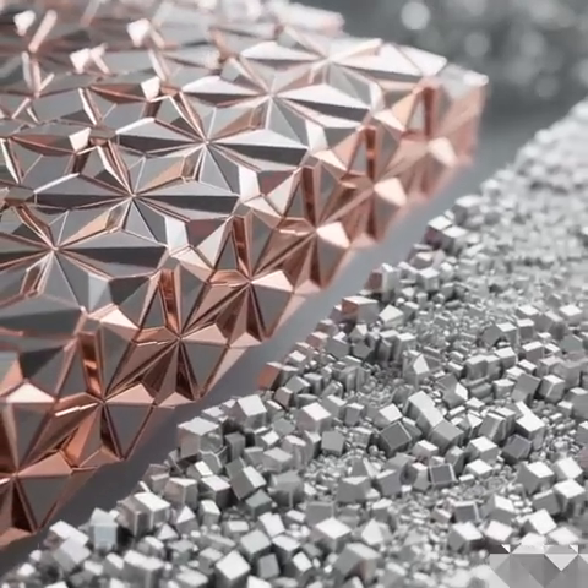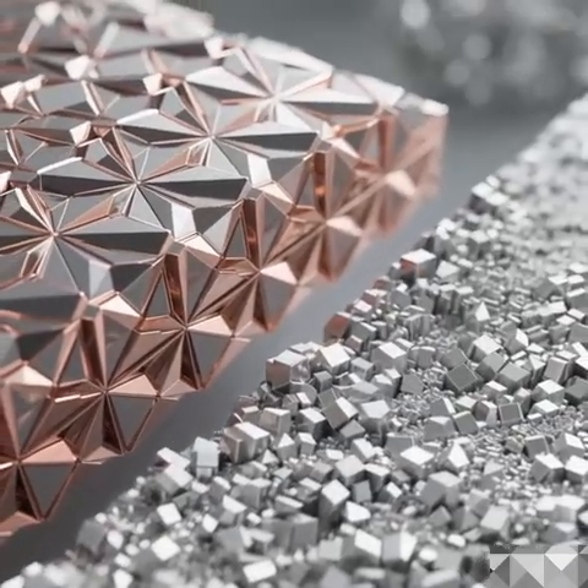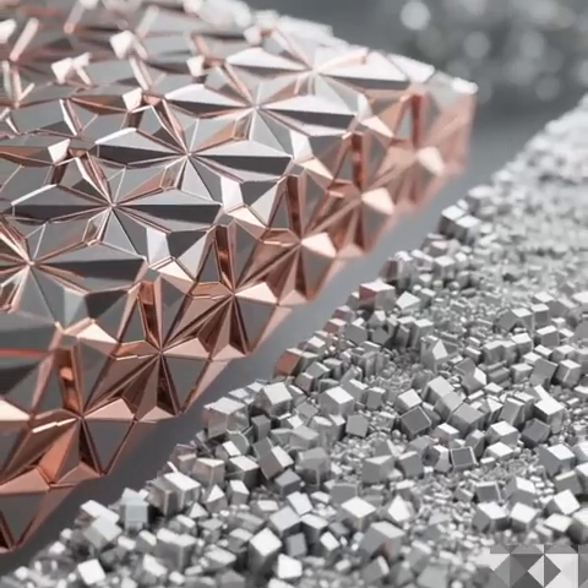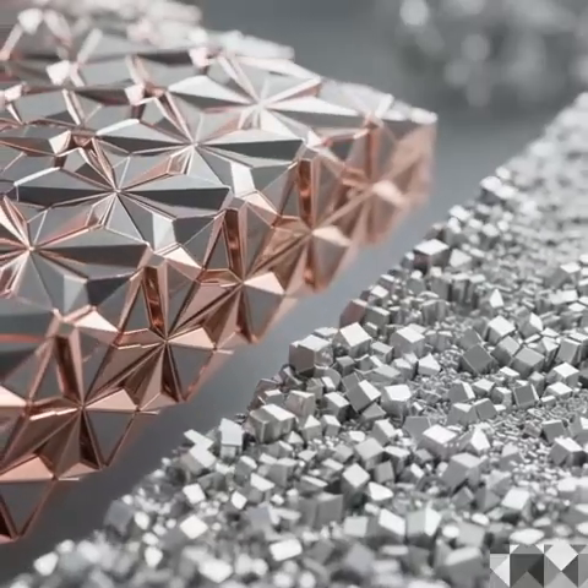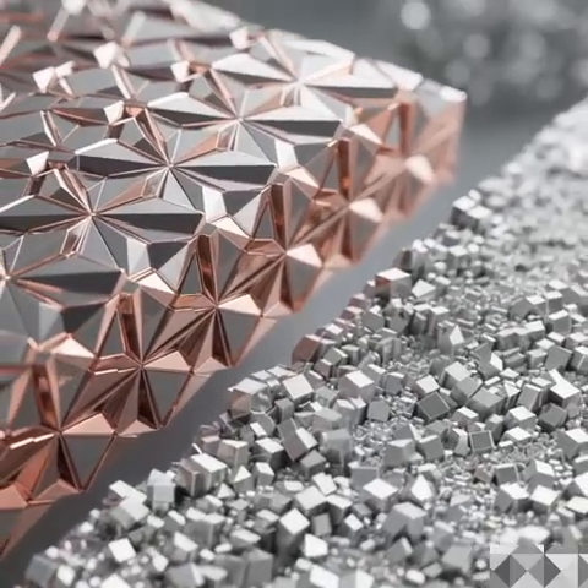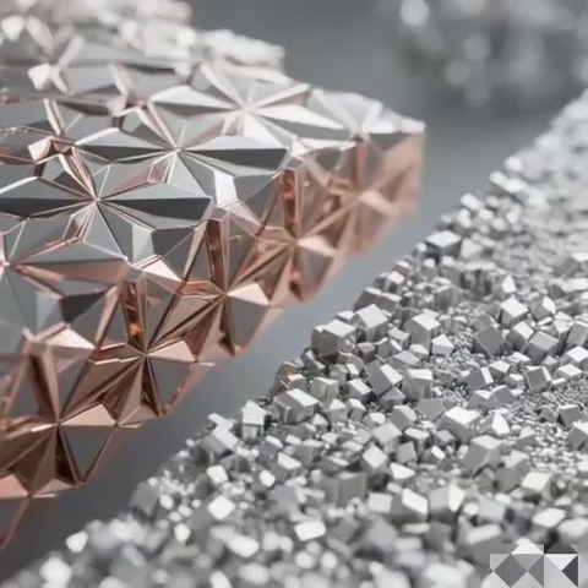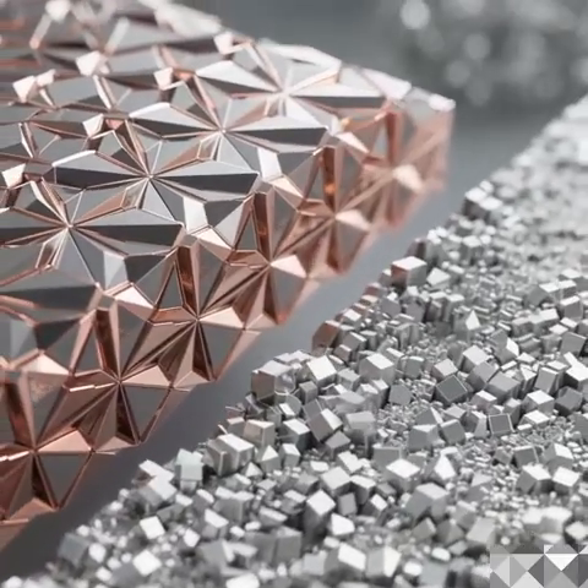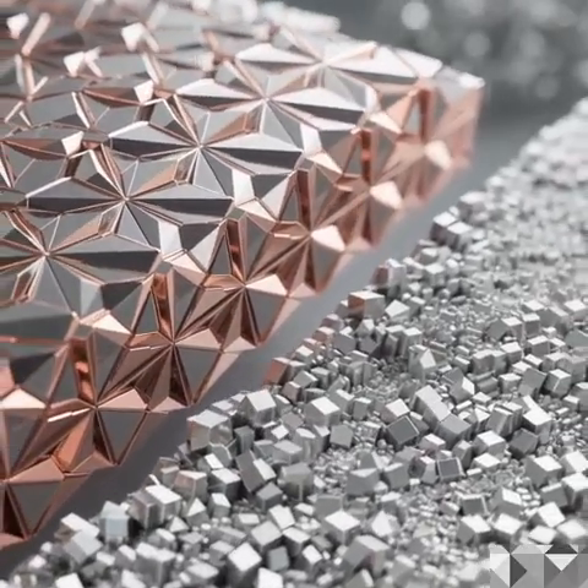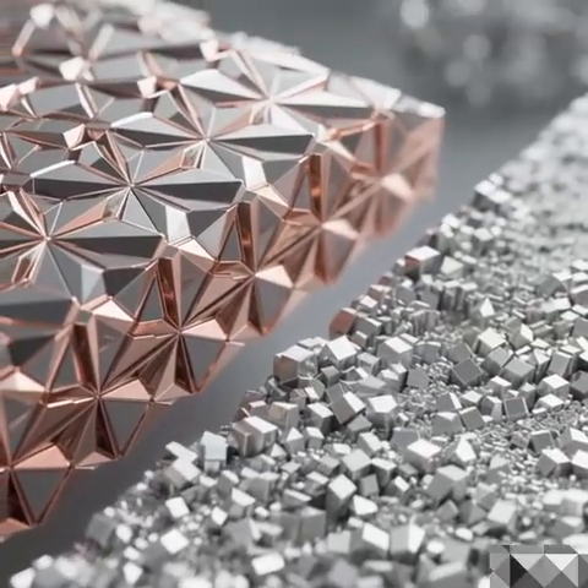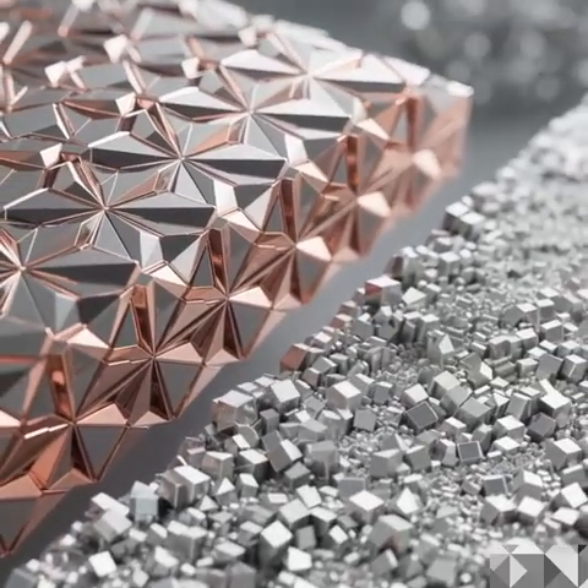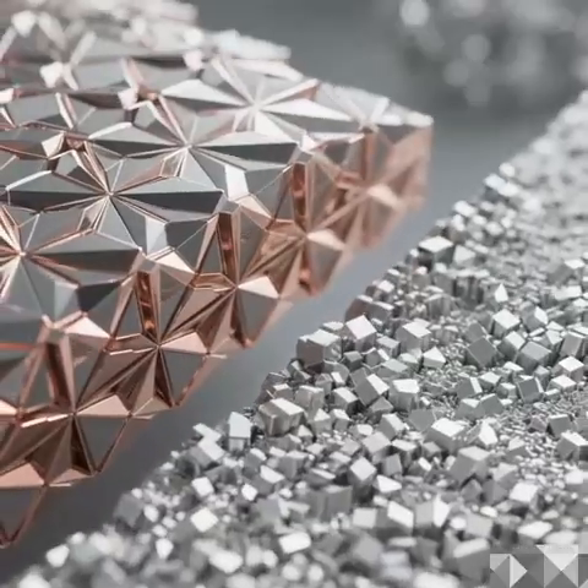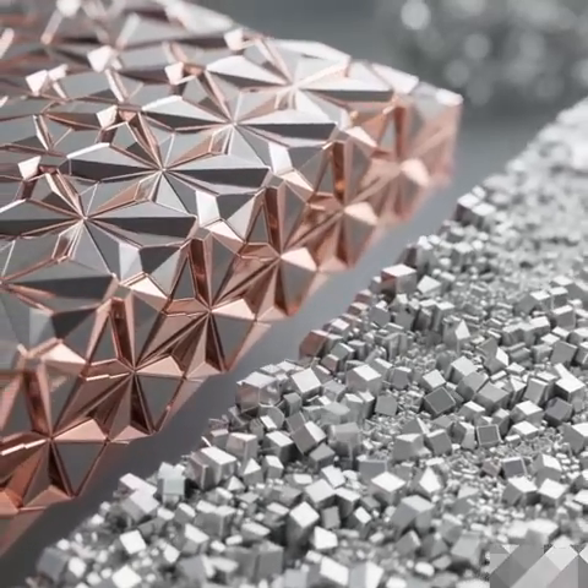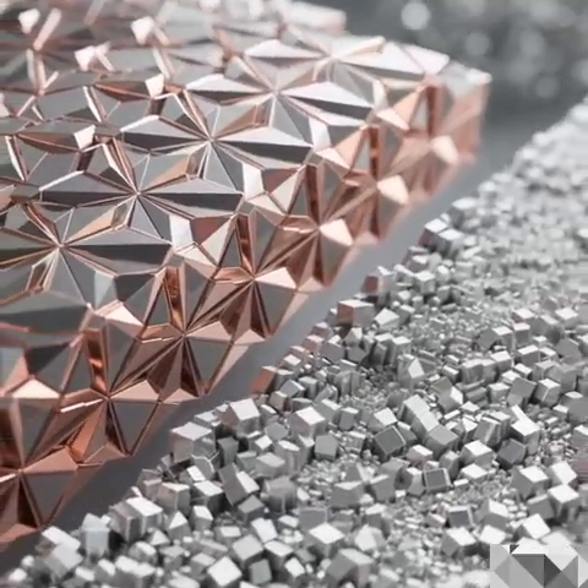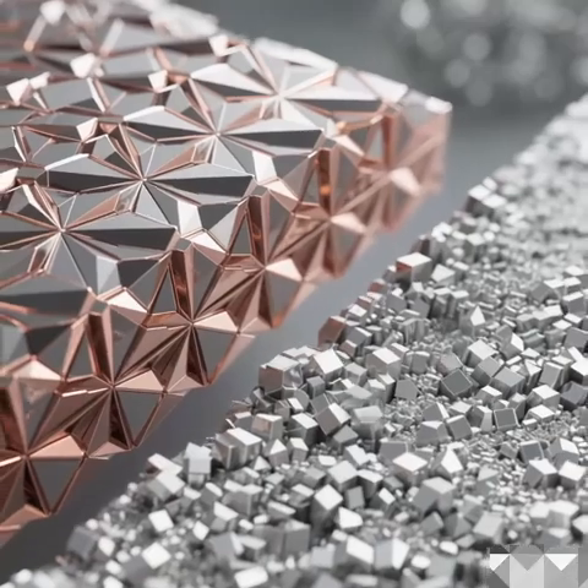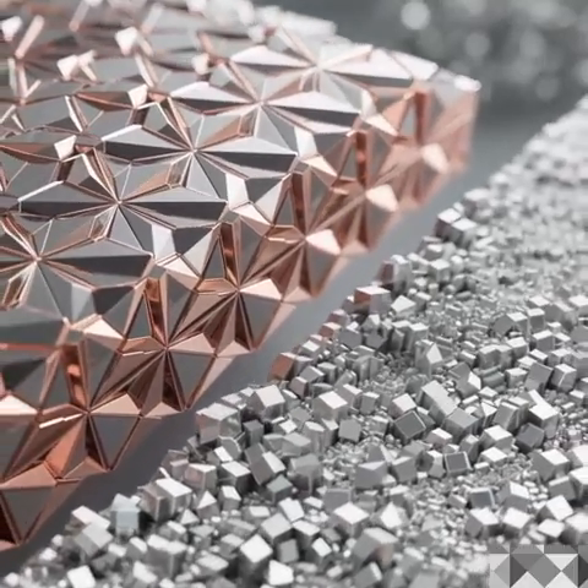And the result for bonding? Temperature and time. That's the other impressive part. With this NC plus CG structure, you can get effective bonding at just 100 degrees Celsius, though it takes about 60 minutes. Still, 100 degrees, that's really low. Or if you can go up to 200 degrees C, it can bond in just 5 minutes. 5 minutes. That sounds incredibly mass production friendly. It really is. That speed and low temperature makes it fantastic for high volume stuff. Think AI packaging modules, components with tons of connections, high I/O density.